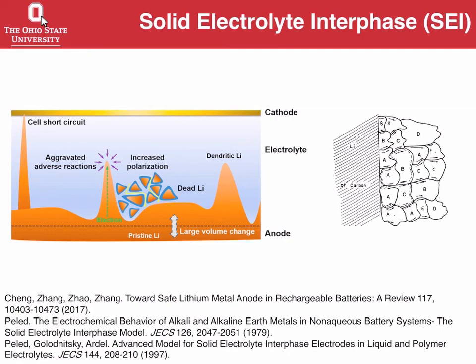You can have many things that happen during the cycling of a battery. One of the most deleterious reactions is when you transport lithium ions, they don't plate in the same way. You could have started off with a beautiful planar lithium chip, and then as you redeposit, you can have dendritic lithium that forms, and then as you can expect, if the lithium grows and grows and touches the other electrode, you can imagine the short circuiting that happens. And of course, we've all seen the reporting at the $2 billion cost scale in terms of that failure mechanism. And thermal runaway is another issue, okay?